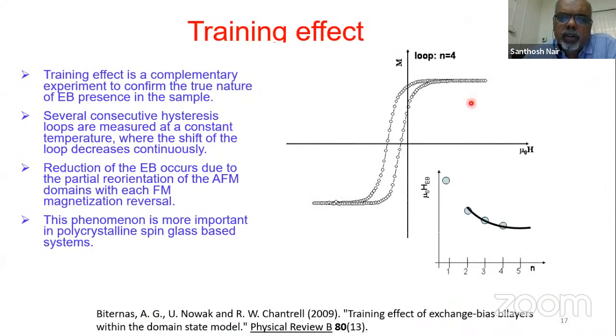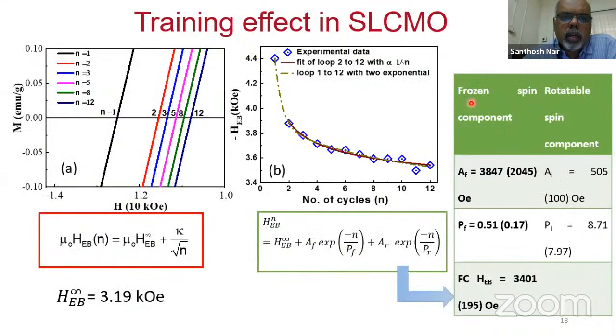Okay. We can also do what you call a training effect study. Where you cool down to the lowest temperature, do a hysteresis loop, you see the exchange bias, but you keep looping many cycles, and then the exchange bias keeps reducing. That's because in a system like this, there is an interface between the ferromagnetic and the antiferromagnetic region, but that antiferromagnetic region at every cycle kind of rotates and things like that. So there is a change at the interface, especially at the antiferromagnetic side. That can lead to this training effect. We can fit this by a particular curve by Mishra et al., which takes into consideration the presence of both rotating spins as well as frozen spins. That can actually fit our curve perfectly, and then we find that this is correct.